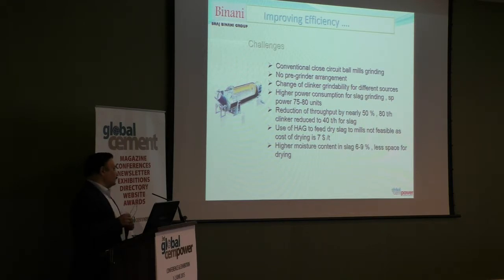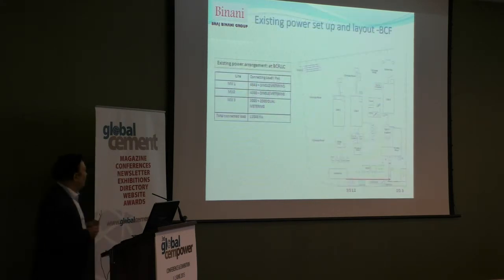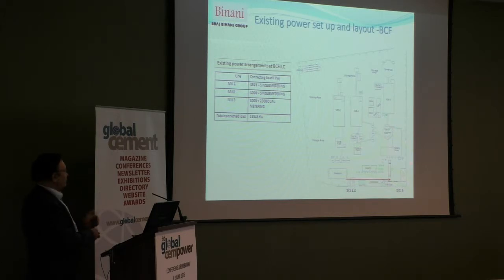Typically what we see is that slag as received material may have moisture varying from 6% to 10%. And this is the average figure. Now this layout will be repeated again and again because I want to show you what we have moved and from where.